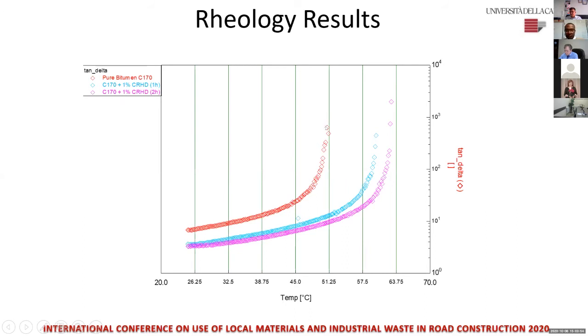You see that here the transition is still around 51 degrees for the pure sample, but the sample we prepared in 1 hour remained at about 60 degrees, which is 10 degrees of difference. After we left it for 2 hours, it increased a little more to about 62, 63 degrees, which means maybe it increases the temperature resistance, or it increased the amount of asphaltenes in the bitumen, which made it a little bit harder. So we're trying to characterize if this is a very good effect or a slight disadvantage.